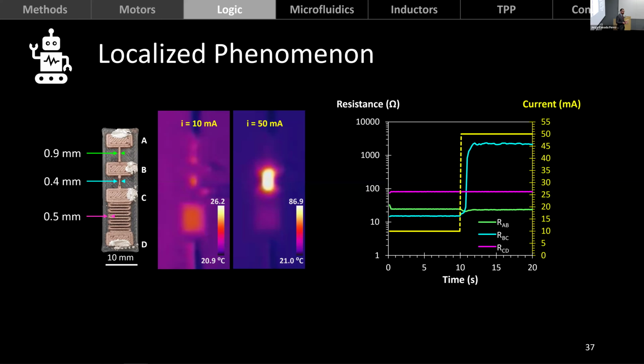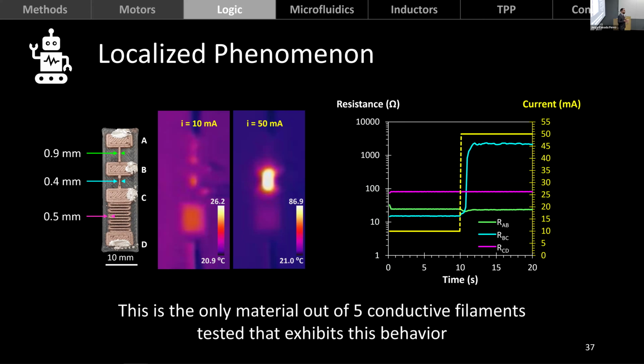And if we look at the evolution of the resistance of each of those segments, we also see that is indeed what is happening. We see that the resistance in the segment AB and that of the segment CD pretty much remain undisturbed throughout the whole experiment, while the resistance of the segment BC spikes soon after we apply the high current. We tested a few different conductive materials for 3D printing, and we found that this is the only one that exhibits that behavior. So it is pretty special.